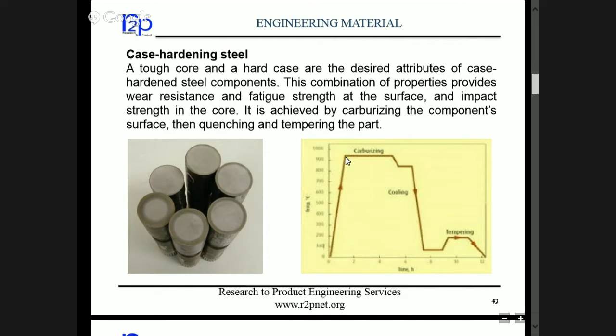So we slowly heat the material, and around 900, 950, we let the carbon absorb into the case, right? The time is maybe 6-7 hours for the carbon getting built in. This time period will depend upon how much case depth we want. If we require say 1.5 mm case depth, maybe we need to keep it at that temperature for 8 hours. But generally the specification given is 0.8 to 1 mm, so we can keep it for less time. In this way the carbon buildup happens, right? After the required carbon buildup, maybe 0.6 or 0.7, because more carbon will not help us. We need to increase the carbon in the outer skin only, 0.6% you can say.